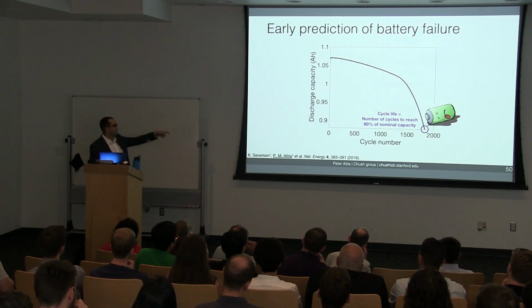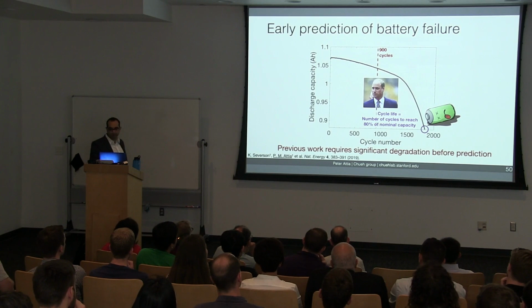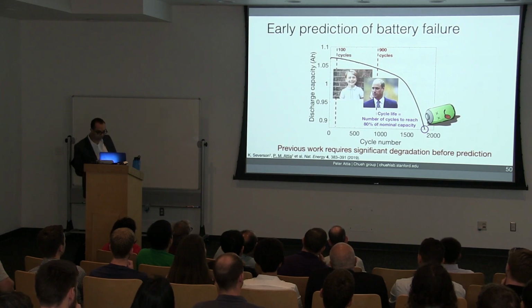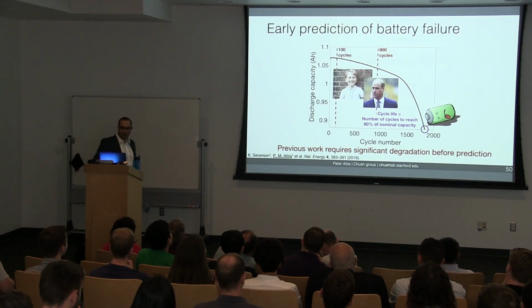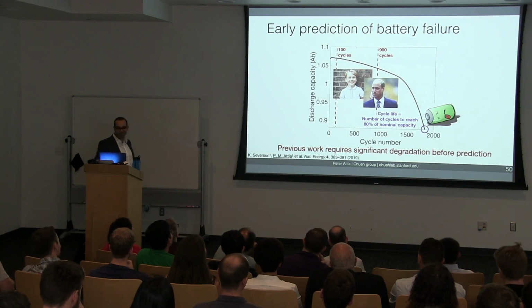To start with early prediction. The goal of early prediction is to predict the final cycle life using only a small subset of the initial data. You've seen this plot before. This is discharge capacity versus cycle number. Now, traditionally, early prediction has been a pretty hard problem. Most previous work is only able to predict the final cycle life after the batteries have already experienced significant degradation. So in other words, we're basically predicting the cycle life of middle-aged batteries. We set a goal of using the first 100 cycles, which is equivalent to predicting the lifetime of kindergarten-age batteries.